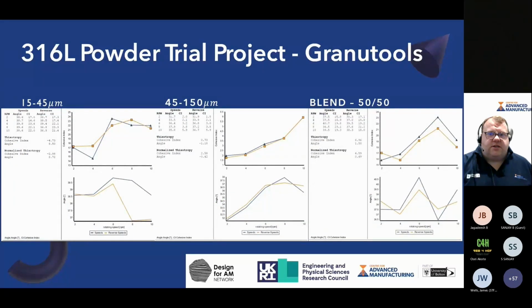It's not really too pioneering at that stage. We then looked at the GranuDrum. In this case, we looked at low speed performance at 2 up until 10 RPM, and then 10 on the way back down to 2. The drum will start to rotate, and it will measure the angle at which we start to see powder fall. That's one of the initial parts. Our calculation in the background will then give us a cohesivity index, and it will start to talk about whether the powder has behaviors, shear thinning, for example, where we start to see powder change with speed, whether we see any hysteresis, where we have different performance on the way up to on the way down.